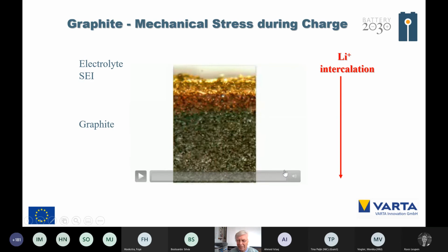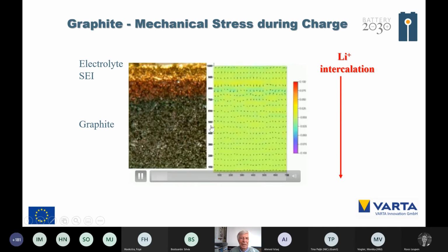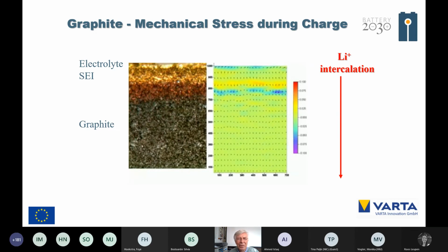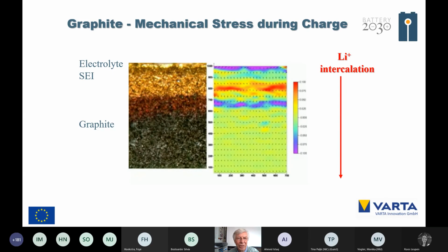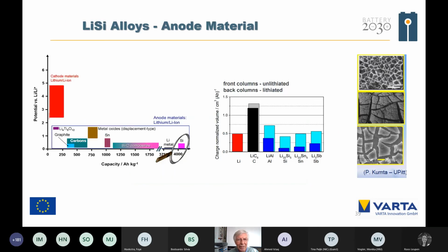If you look, for example, at the mechanical stress in the graphite electrode: here is the SEI, and now the lithium intercalation is going on. And you can see here the volume stress going into the graphite via the charging time. And that stress in the graphite also has a feedback to the SEI, because that stress cracks the SEI, and then the electrolyte can react much faster with the graphite.